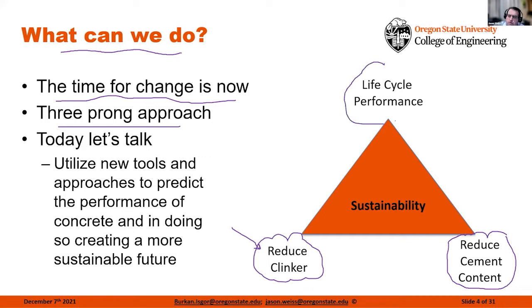The final leg of the stool is really looking at performance. And there are cases that we've demonstrated where if you use, for example, internally cured concrete, you can triple the service life of your concrete bridge deck by reducing cracking and increasing durability with modest costs. We're looking at about a 3% materials cost, which is about a 1% bridge cost, but we're getting triple the life of that concrete. And that makes a huge difference. And we think the way that we're going to bring in these new tools and we're going to use new industrial byproducts and we're going to create a more sustainable future is by improving how we model these systems.